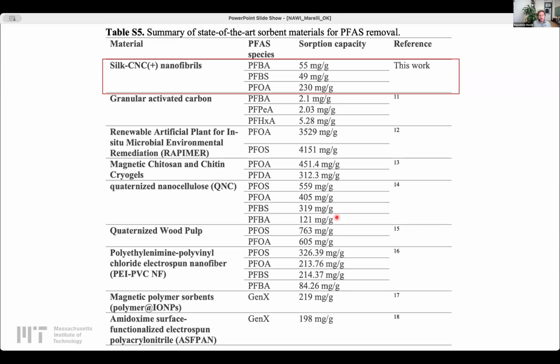To conclude, I would say that this is a technology that we're still developing. We started with silk and cellulose nanocrystals because those were two materials that we had available in the lab. We're now expanding the portfolio of biopolymers that we're using to generate these membranes, and we're testing how different biopolymers extracted from different biomass have an impact on the sorption capacity, the stability of the membrane, the anti-fouling properties, and at the same time the price cost that we can think we can have. Given that this is, of course, one of the most challenging parts when it comes to PFAS filtration, be sure that the price is low enough.